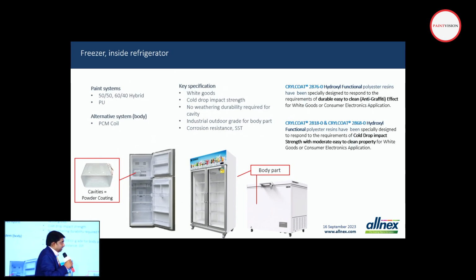Yeah, another segment is the freezer. Nowadays, a lot of freezers are kept outside of the shops, open in the atmosphere or exposed to natural weathering. So for that, we have 2 solutions. One is 2876. This is a hydroxyl functional polyester resin. This is the highest easy to clean, meaning anti-graffiti resin. It even passes all the magic inks, which are very critical to pass. Then we have economical grades as well, 2818 and 2868. Generally, if you are talking about the outer body part, for the freezer segment, for higher functionality, we generally suggest using PU powder paint on this system.